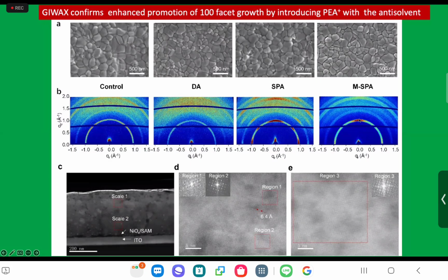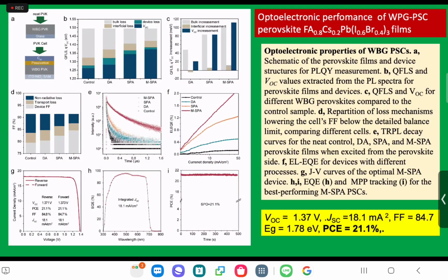And so this is the stunning thing. Here we have uniaxial 100 crystals that form the film. Very impressive. And so that leads to some desirable optical properties, the voltage deficit goes down, and that's of course what we need for the wide band gap. And you can see the fill factor, also the losses there. You minimize these losses, especially transport. And the emission, that's lifetime of the luminescence. All this looks very good.